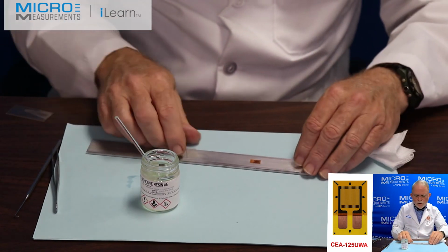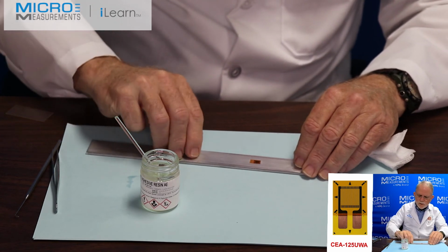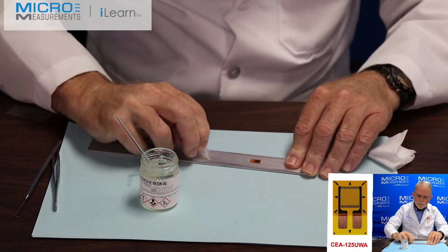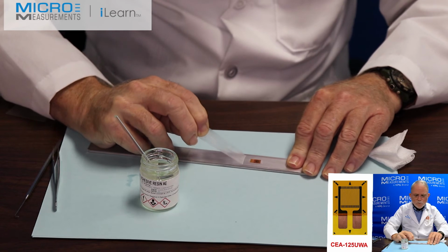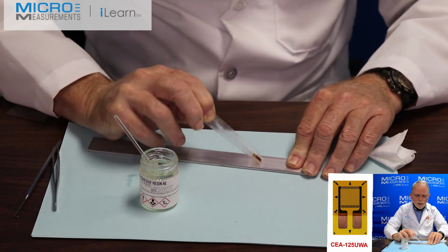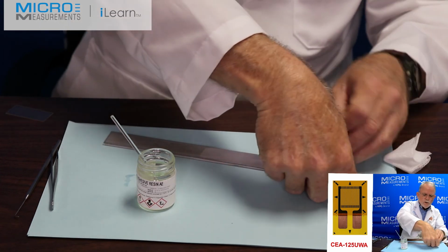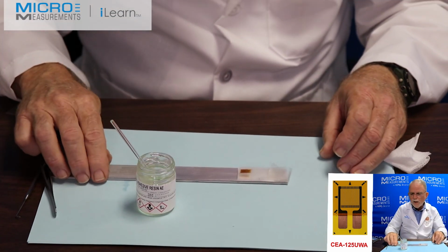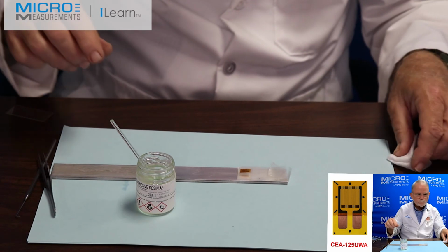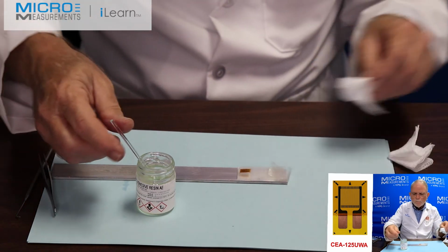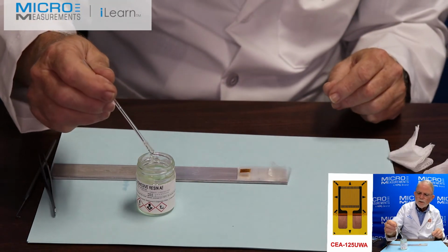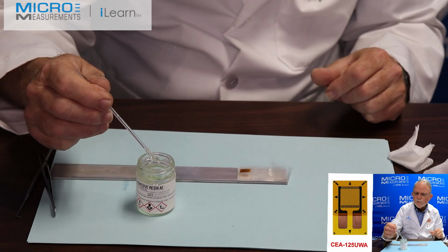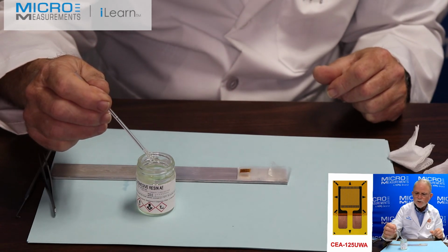Now, before, we're going to lift the tape at a shallow angle. We don't want to damage the gauge as we're lifting it off the beam. And I'm going to expose the bonding surface of the 125 UWA strain gauge. I'm going to take the stirring rod and I'll pick it up and let 2 or 3 drops of the adhesive drop off of it. Don't want to put too much in the gauge site.